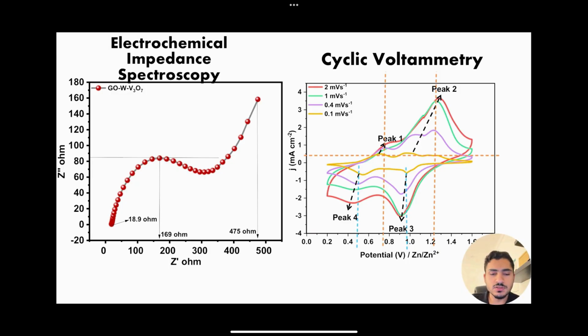Cyclic voltammetry shows the redox nature in the battery, where we have the upper peaks for the oxidation in the anode, and the lower peaks for the reduction in the cathode. It also shows the potential and current for those peaks. The highest anodic peak shows a current of around 3.5, which is higher than the highest cathodic peak, whereas the second anodic peak shows a current of around 1.3 milliampere, which is lower than the second cathodic peak.